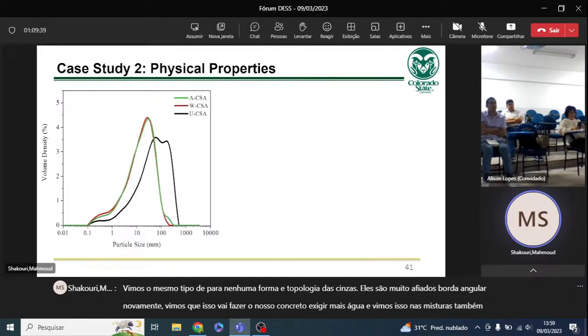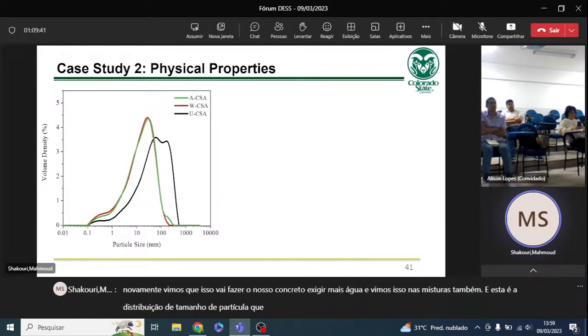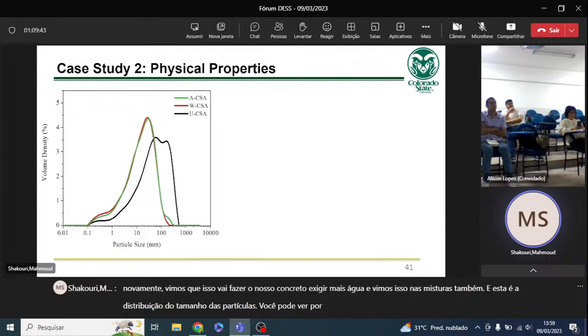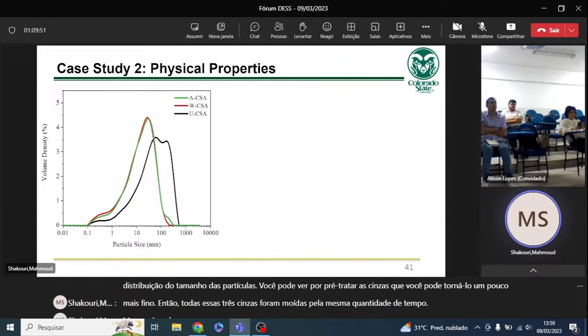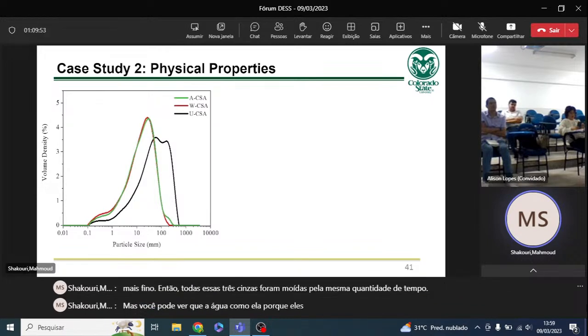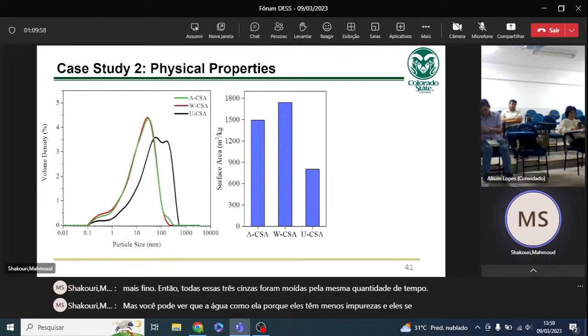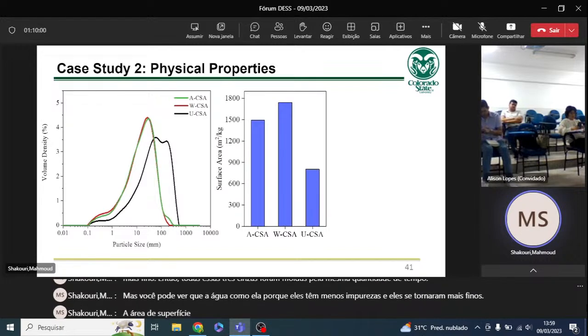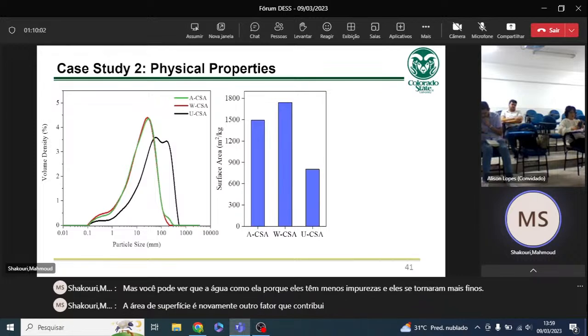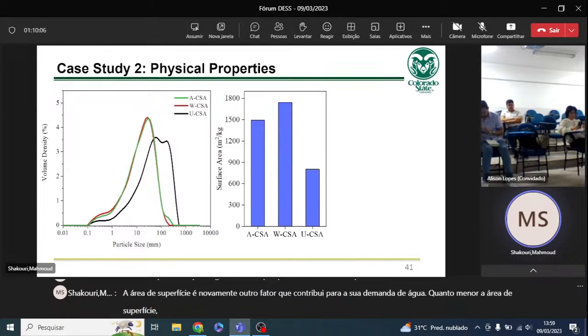This is the particle size distribution. You can see by pre-treating the ashes, you can make them a little bit finer. So all of these 3 ashes were milled for the same amount of time, but you can see that the water and acid ones, because they had fewer impurities, became finer. Surface area is again another factor that contributes to your water demand. The lower the surface area, the lower the water demand.